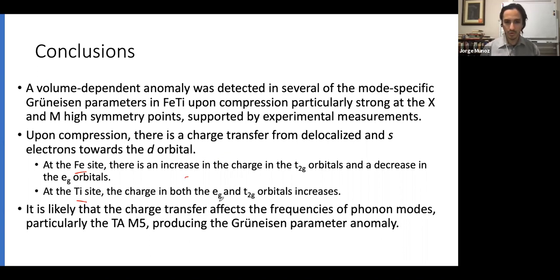For titanium, both the EG and T2G increase the charge. For iron, the T2G shows an increase, but the EG shows a decrease. It is likely that the charge transfer affects the frequencies of the phonon modes, particularly the transverse acoustic M5, and produces this Grüneisen parameter anomaly. Thank you very much.